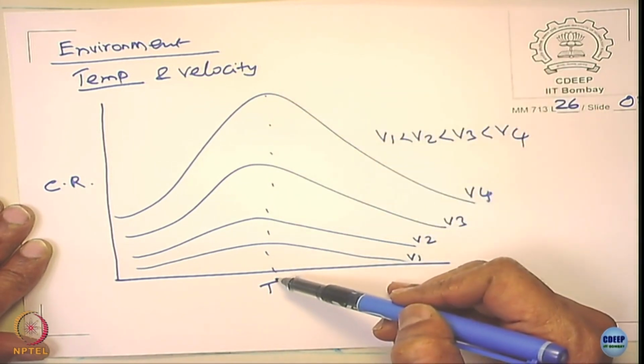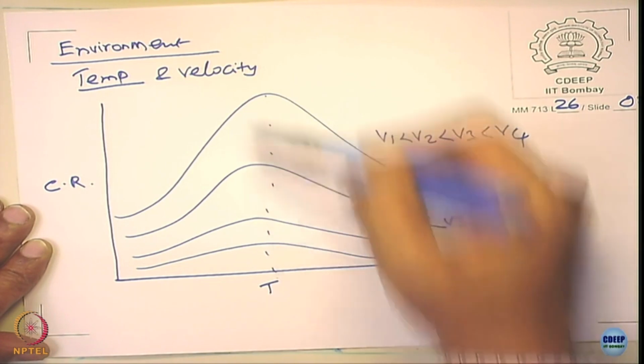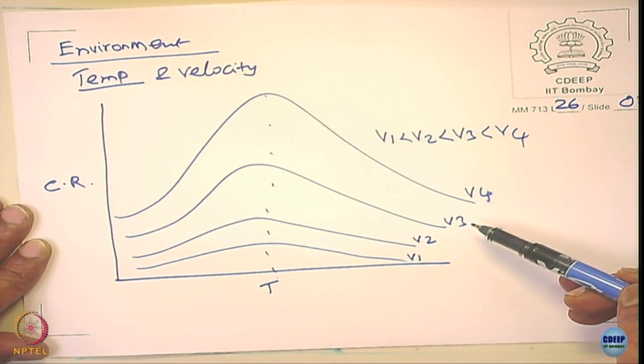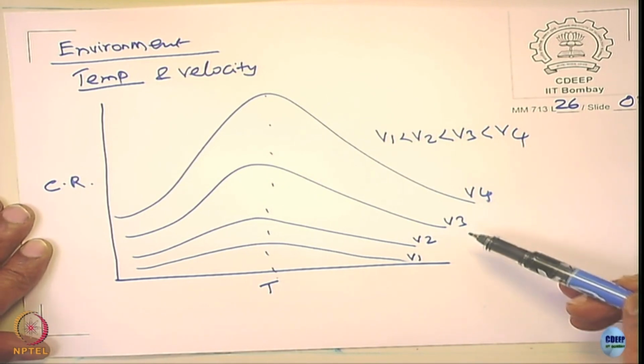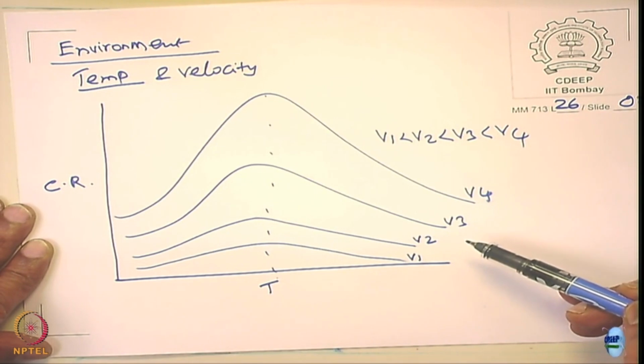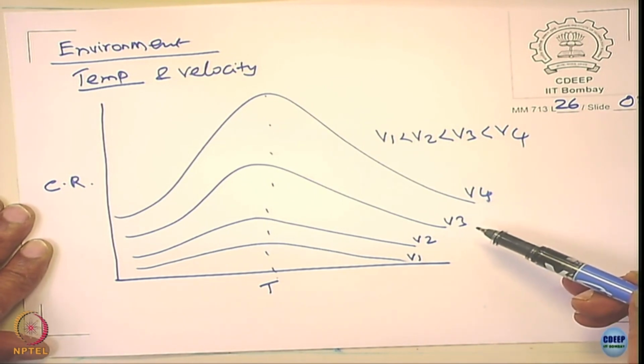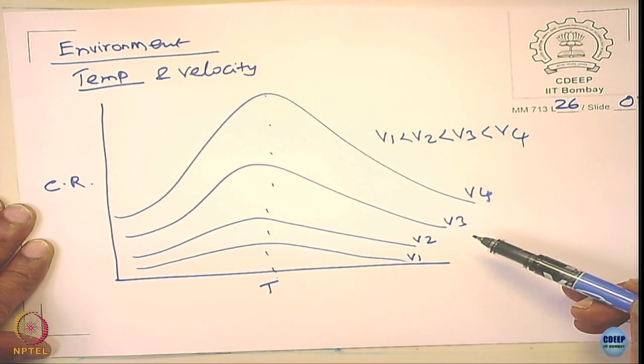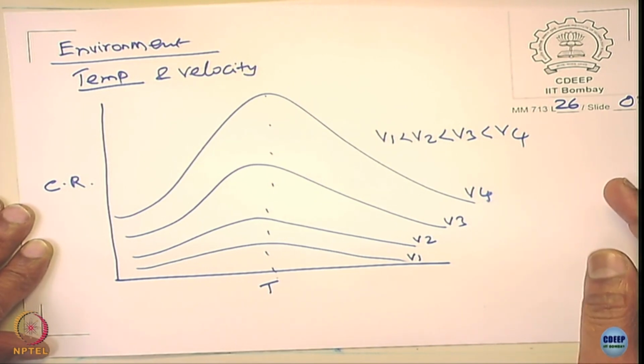it increases steeply at this temperature. With temperature it rises and then there is a drop in the corrosion rate. So it is a very unusual thing that you notice for any corrosion process. It is not the same as what we discussed earlier, the effect of temperature on the corrosion rate of water. I said that when you raise the temperature above 85 or so, the corrosion rate of water drops because the oxygen escapes from the water. In a boiler that does not happen, the oxygen cannot escape, nor is oxygen present in this water at all.